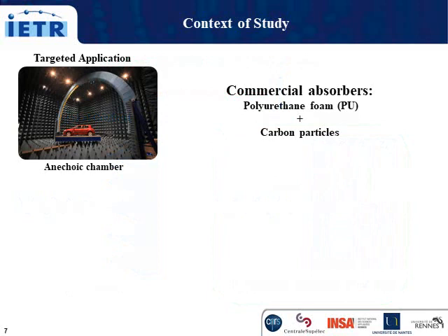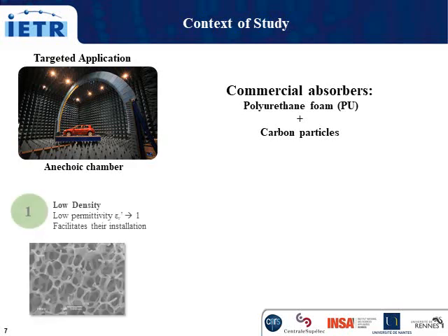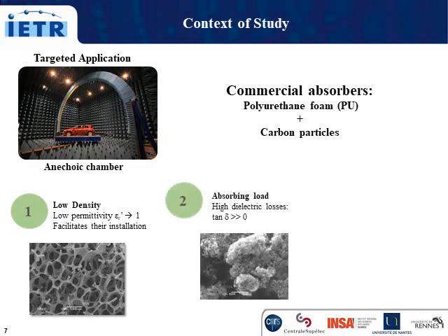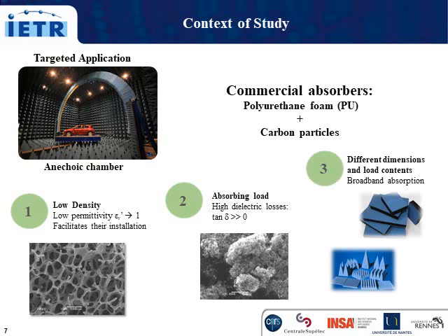Today, absorbers used in the anechoic chamber are often in the form of pyramidal or multi-layers made of polyurethane foams loaded with carbon nanoparticles. The advantages of these absorbers are their low density, which facilitates their installation in the anechoic chamber, and their loaded carbon particles, which ensures good absorption performance in a wide frequency range. In addition, the frequency range and performance of these absorbers can be adapted by varying the carbon content and dimensions.